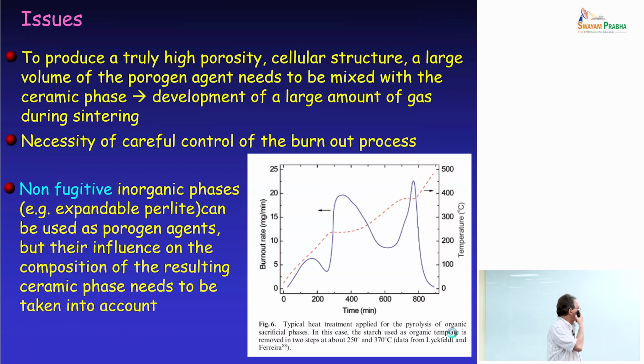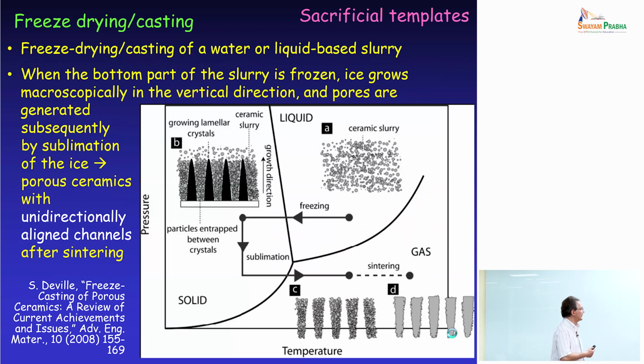You have, of course, issues in terms of gas evolution, so you need to be able to carefully control the burnout process, but people can do that. And this is a very cheap way of obtaining a large volume of porosity, even though the morphology of the pores is not always very good. You can also use non-fugitive inorganic phases.